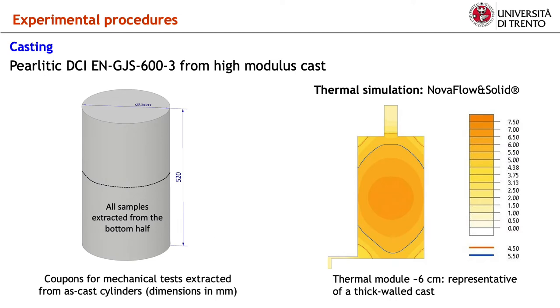In this work, the experimentation was carried out on a pearlitic ductile cast iron GS600. The specimens were extracted from a mass cast cylinder of high thermal modulus exposed to natural air convection, thus representative of thick-walled castings subjected to long solidification times. All the samples were taken from the bottom half of the cast cylinder in order to maintain a certain uniformity in microstructure and defectiveness.